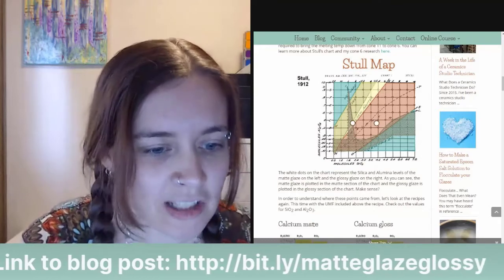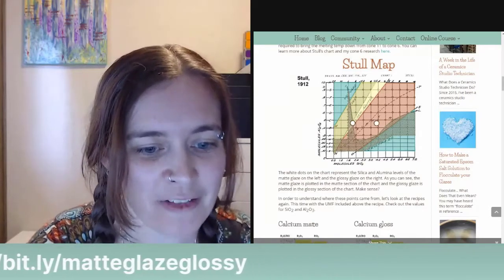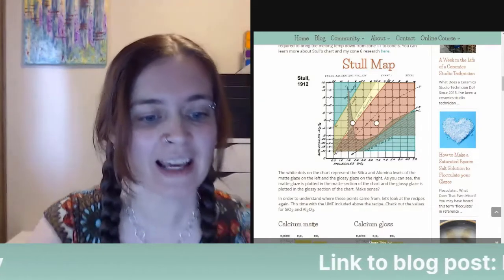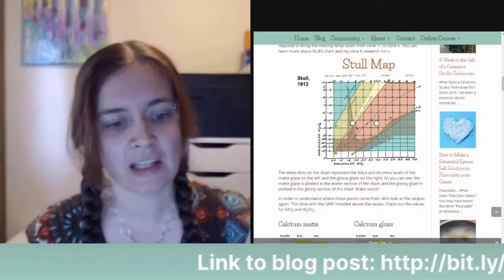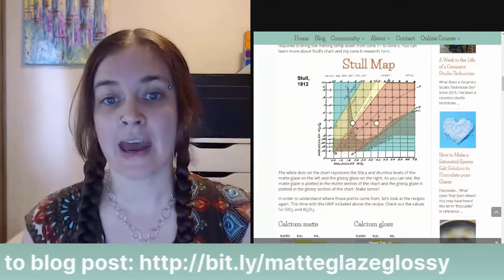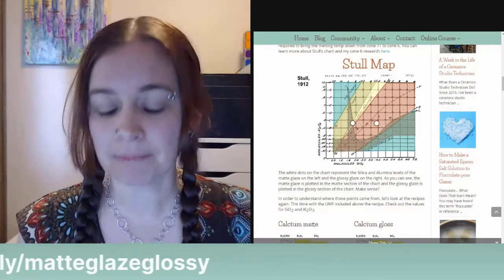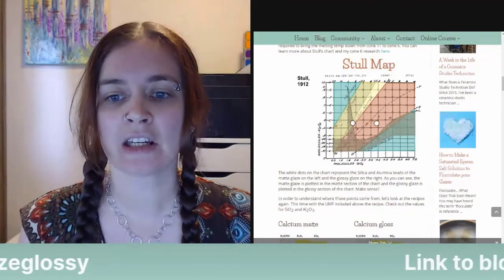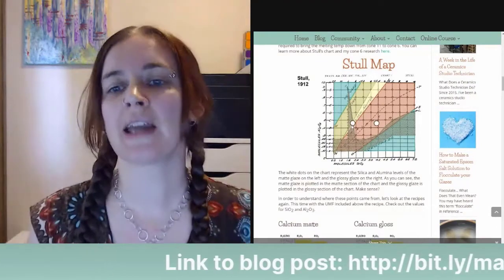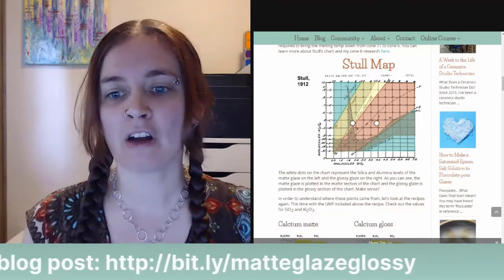Andrew has another question. Andrew says, all my low fire glazes are glossy apart from a crawl with magnesium carbonate. I'm excited to try reducing the silica to get some mattes. If not underfired at the glaze stage, would these new matte glazes be just as food safe as their glossy counterparts? Yes, so that's the thing: when you have a matte glaze that falls into the matte region of the Stull chart, that's the true matte glaze, meaning that it's properly melted and it's not underfired.